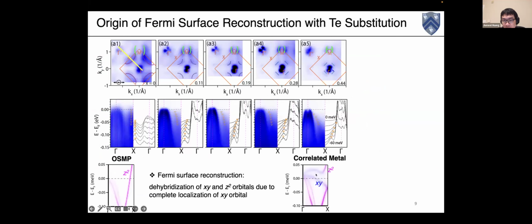I'm sorry, what's the first question? The first question, maybe I missed that point that you explained: what is the relationship between the orbital selective Mott transition versus the appearance of this Z square band crossing the Fermi level? Does it mean that the XY band just completely disappeared and all of a sudden you're just seeing the Z square band? Yeah, because the XY band just completely disappears, so then the Z square band will cross the Fermi level and form this band around the X point.